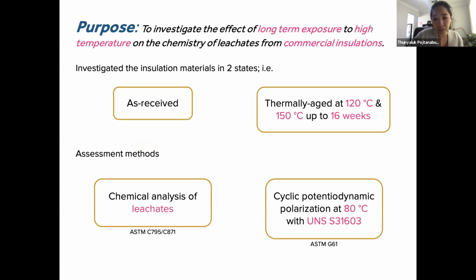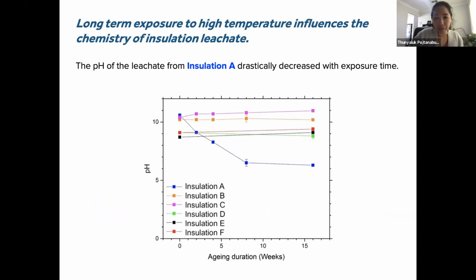So what we're trying to do here is to look at different types of insulation materials and to see whether or not the chemical properties change, and how it affects the susceptibility to pitting corrosion of 316 stainless steel. So we ran cyclic potentiodynamic polarization at 80 degrees with 316 stainless steel. We tested the insulation as received and as it's thermally aged. So let's look at the first insulation, insulation A. In this one, it was fibrous mineral wool insulation.